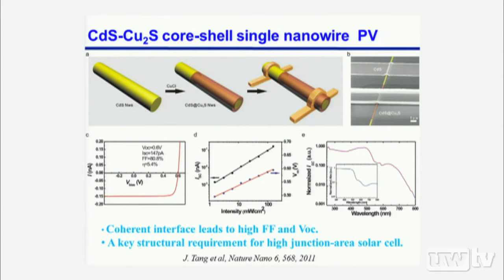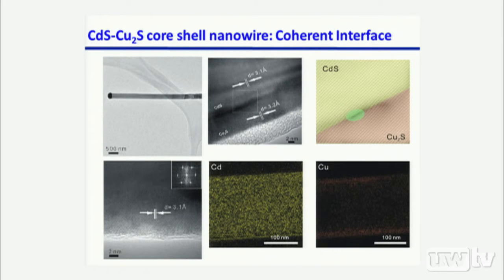We are now pushing to increase the thickness of this copper sulfide shell so that we can push this efficiency above 10%. I think that's quite a promising direction. And this tells you about the interface. Through this very mild cation exchange chemistry, we examined the interface between these two materials, cadmium sulfide and copper sulfide. Indeed, they are very coherent, with not many defects at the interface. And I think that is the key structural feature that gives us a very high fill factor in this nanowire solar cell.